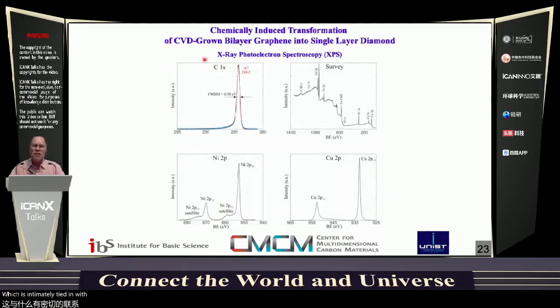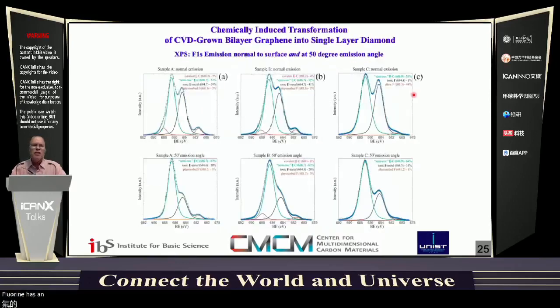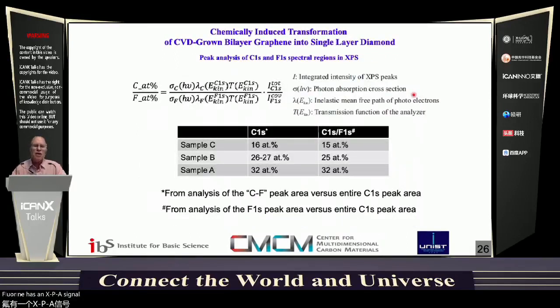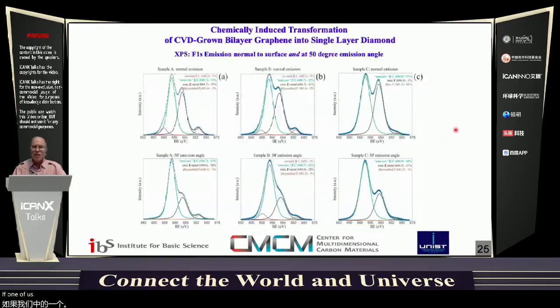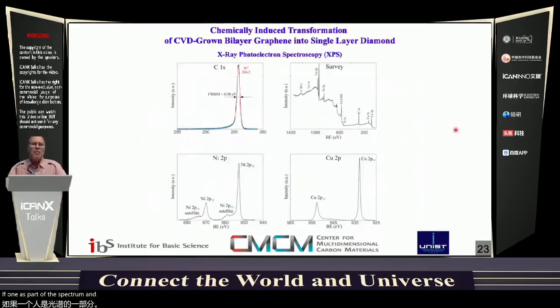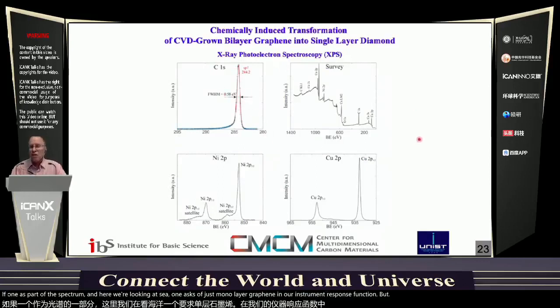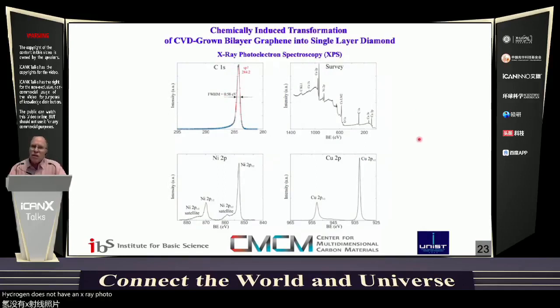with Pavel's X-ray photoelectron spectroscopy studies. So actually, Pavel made a very judicious choice to use fluorine rather than hydrogen. Fluorine has an XPS signal. As we see here, I'm going to come to talking about the F1S part of the spectrum. And here we're looking at C1S of just monolayer graphene in our instrument response function, but hydrogen does not have an X-ray photoelectron spectroscopy signal.